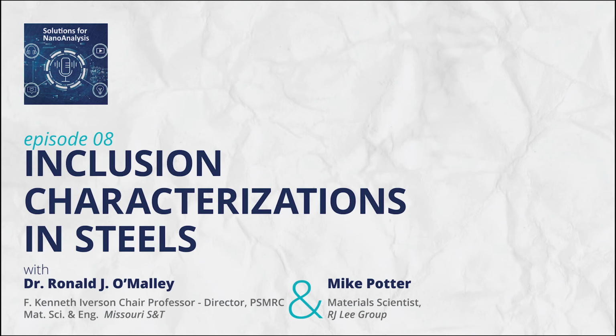Generating new inclusions late in the process is exceptionally bad for the casting process because it causes clogging of the refractory components and ultimately can result in shutdown of the caster due to lack of supply of steel, because these oxides will build up and clog the delivery systems, the shrouding systems that are used to try to protect the steel. So if we can identify those points, we can fix the problems. That's certainly one great benefit.